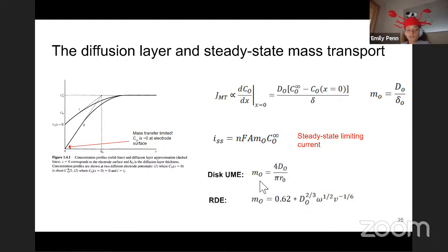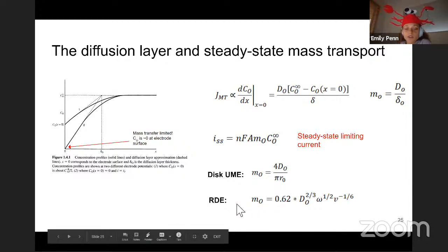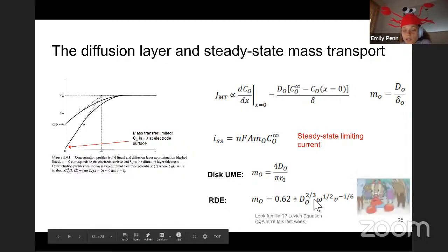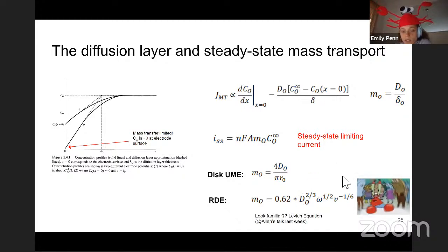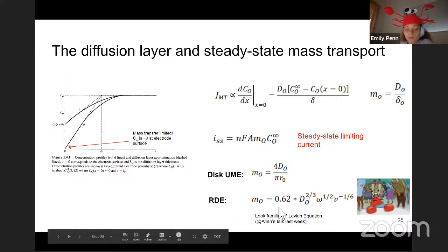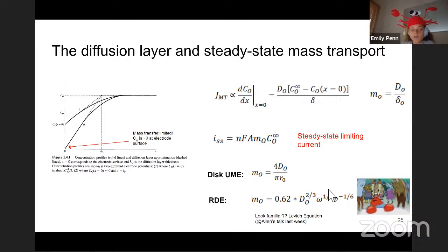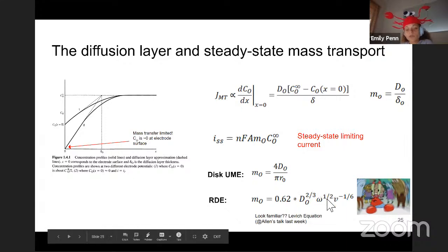And the mass transport coefficient has different functional forms depending on what type of electrode you're using. So for a disk ultramicroelectrode, it's a function of the diffusion constant and the electrode radius. For the rotating disk electrode, this equation might look familiar from Alan's talk last week. This functional form here is found in the Levich equation. But for the mass transport at an RDE, it's a function of the diffusion constant and the rotation rate, as well as the kinematic viscosity of your solution.